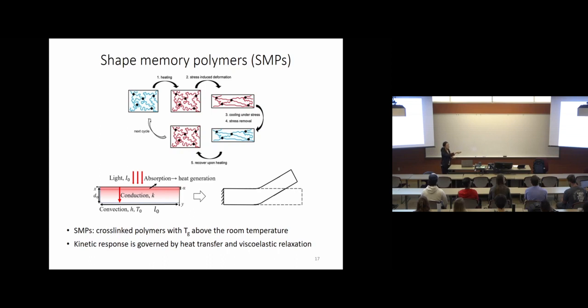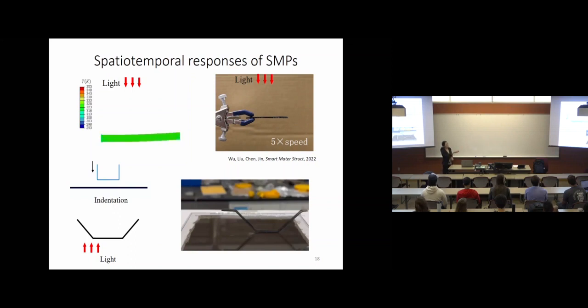Therefore, due to the temperature gradient, the top surface will shrink back first, while the bottom surface is still elongated. Then you can create a bending. But when you shine light for a longer time, such that the temperature everywhere is above Tg, the shape can further recover. So you expect a bending and then unbending process, even if you fix the light. Indeed, by simulation and experiment, we can show this process. You uniformly shine light, and you can see the material undergo this bending and unbending process.